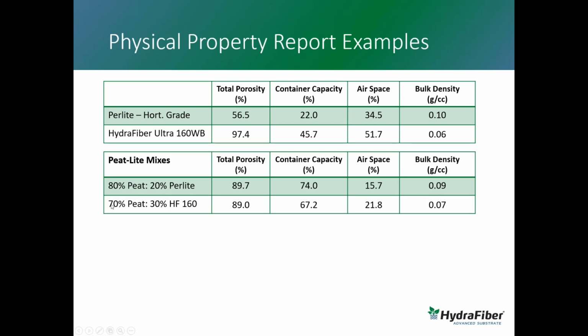And what they tend to transition to would be a 70% peat, 30% Hydra Fiber mix. We see of these two blends that they're both very similar total porosity. They're both in the upper 90s. We see in our container capacity that the peat-based mix has higher water holding capacity than the Hydra Fiber mix does. But we see here that the airspace in this particular example is greatly increased in the Hydra Fiber mix.